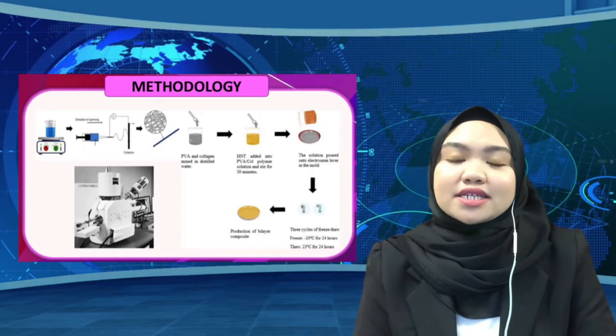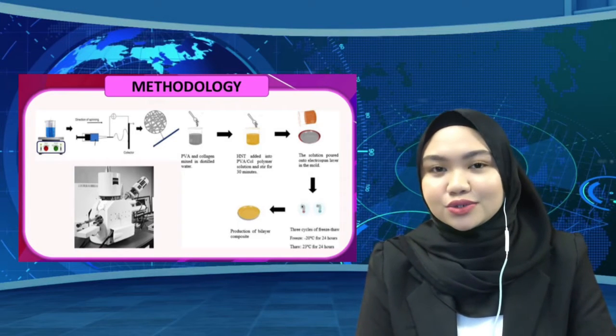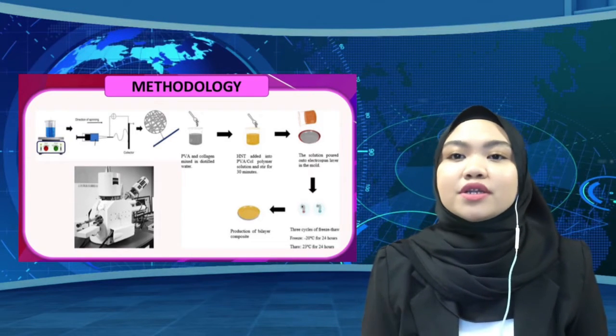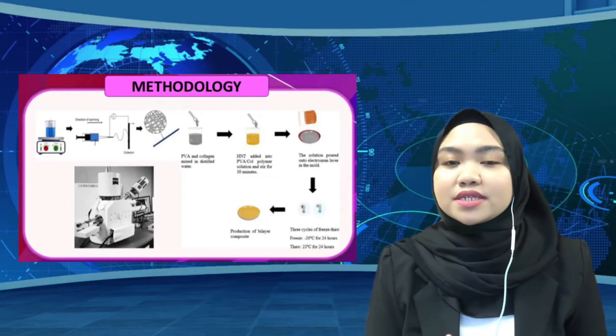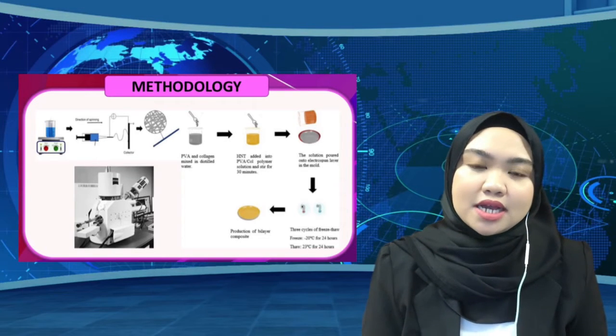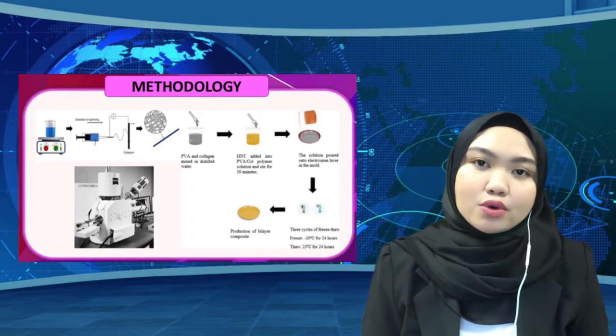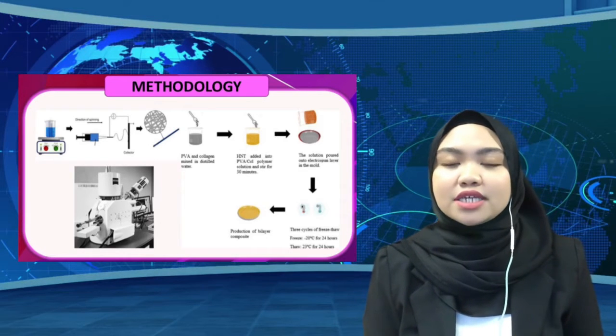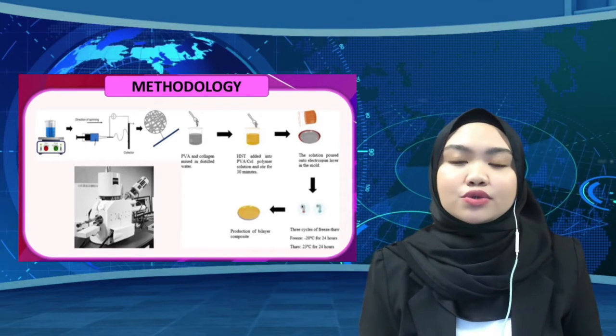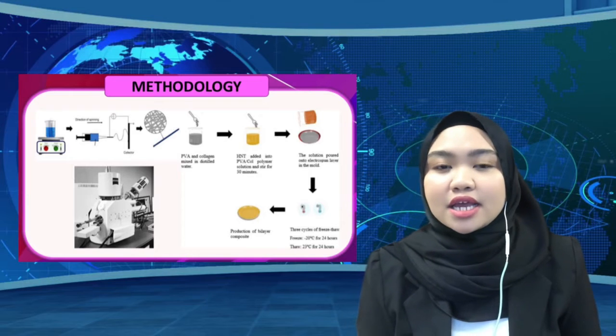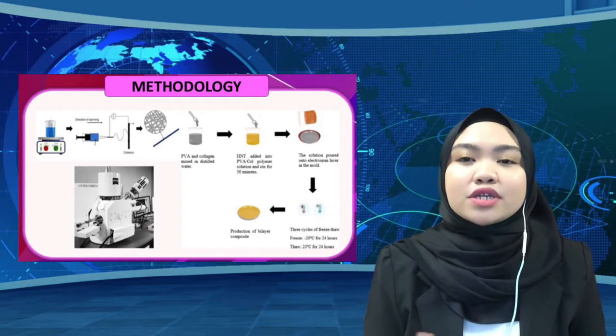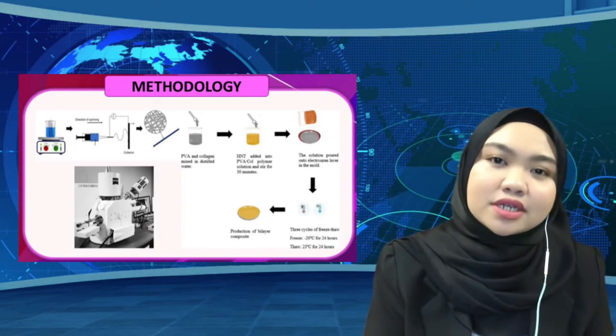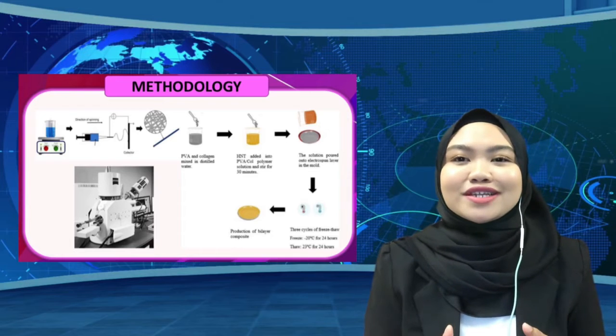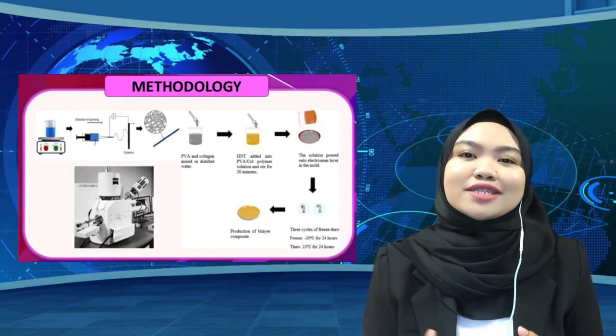So the last one is drug loading testing. The model drug, bromelain, was loaded into the different composites using the post-loading method. The samples of composite were immersed in 200 mg and 400 mg saturated model drug solution at 32 Celsius, and 1 hour was the optimum condition to ensure maximum drug load. The drug composite was then weighed and the drug load was determined by using an equation.